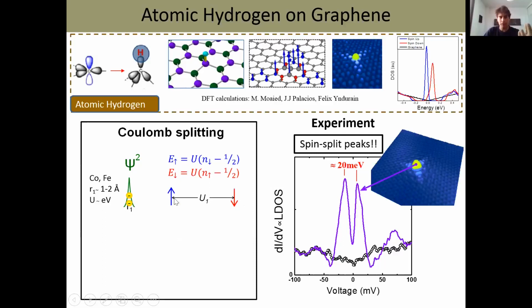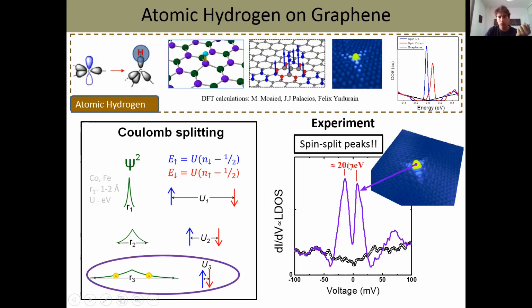So a way to make this separation smaller is to make the interaction between the electrons smaller, and this happens when you have a larger magnetic orbital. So if you make it larger, the U gets smaller, and the separation of the states gets smaller. And eventually, if you make it very large, if you separate a lot the two peaks, then you will have a much more modest separation between the two peaks. And that's the situation we claim to have. We say that here the peaks are separated due to Coulomb splitting, and the separation is small because the state is very extended. And since we have a completely occupied and almost completely empty state, we can say that the separation gives us the U. It's given by the U of the system.